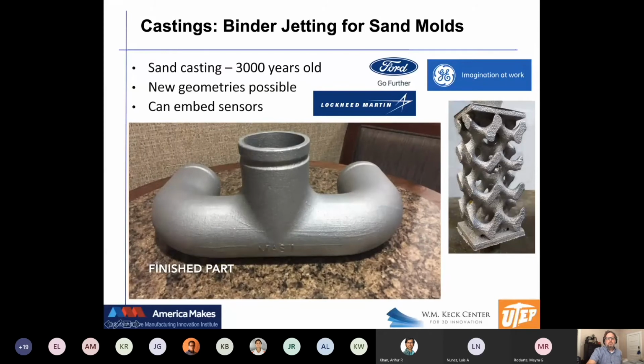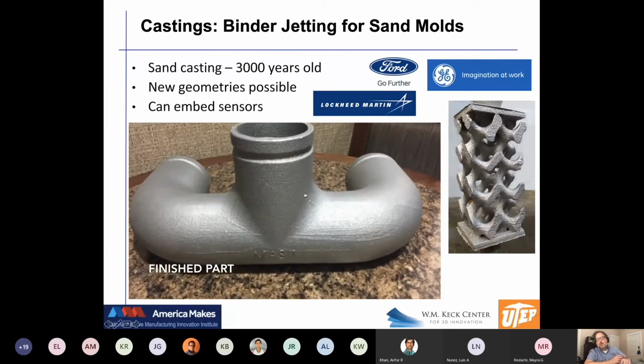And I could scan your head, and I could pour metal, and I could make a statue of your head, and I could do that in about 3 days, and I could probably do it for $400. And casting, of course, is an ancient manufacturing technology. So what's cool about that is people trust it. They don't trust 3D printing, but they trust casting. But if you can 3D print the mold and then use a trusted process, you get the benefits of both worlds. I'm working with Ford, GE, Lockheed Martin, a lot of interest in this. But that's not what I do.